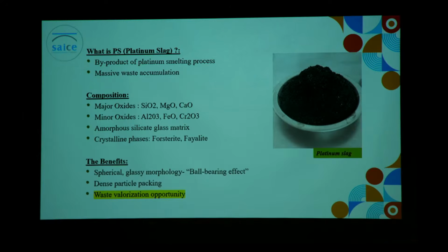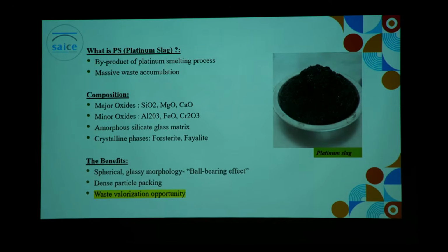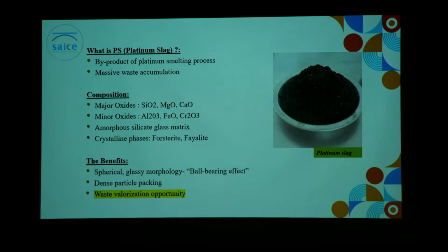The second material is platinum slag waste, the byproduct of the platinum smelting process, which is present in abundance in our country. We look at its composition with its major and minor oxides, but most interestingly, the amorphous silicates and glass matrices, which give us a spherical and glassy morphology, producing a ball-bearing effect. The ball-bearing effect is a reduction in friction between concrete particles and aggregates, increasing the workability of the concrete mixture. Other benefits are denser particle packing within our aggregates, and the key benefit of valorizing the industrial waste produced in the country.